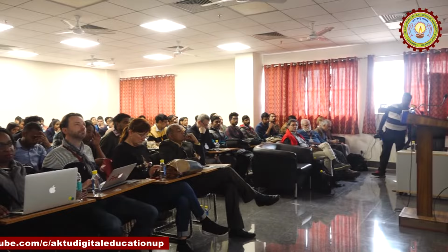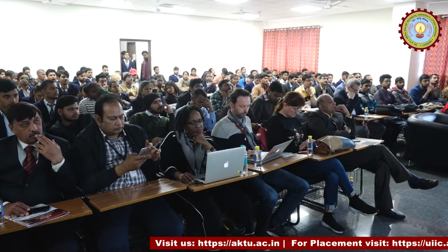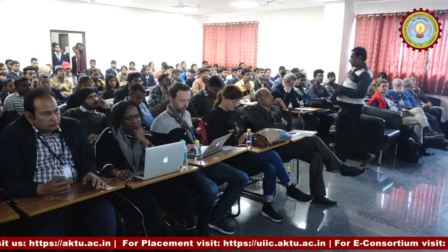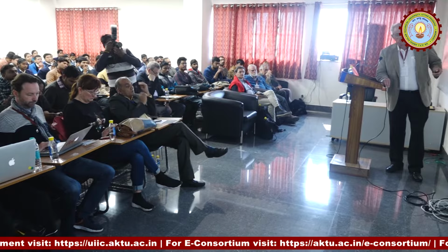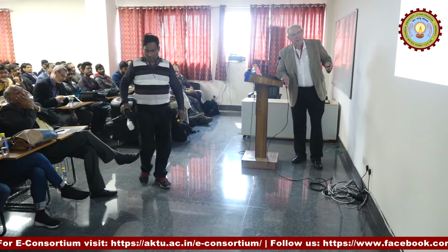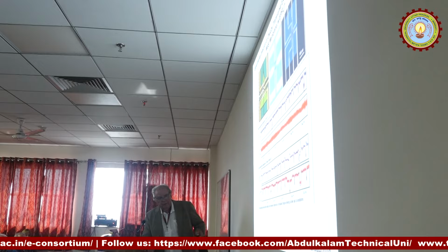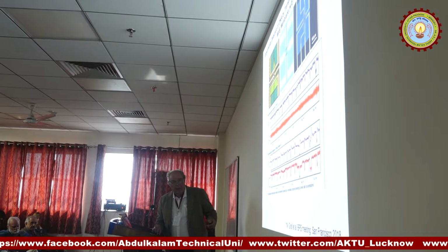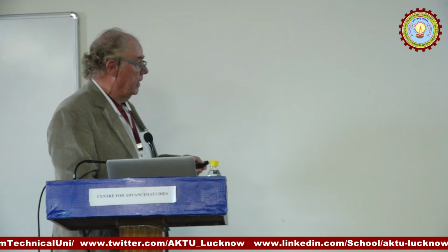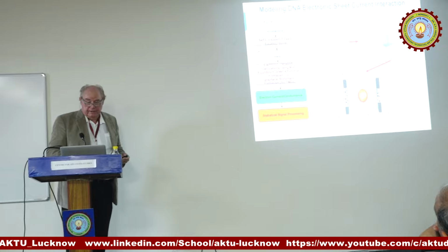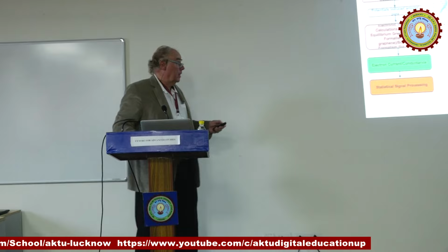Now, we haven't achieved this, but we are now collaborating with the group of Professor Aleksandra Radenovic, which detects electronically now, not only ionically. The dip here detects the DNA. But this is for a certain salt concentration. She had one molar potassium chloride in the material, and as you can see here, we have a lot of noise, but if we can reduce the concentration of the salt, you have a good correlation between the membrane signals. Here is the electrical engineering part. So we had to merge a code, and this is a very intensive kind of simulation process which requires very expensive computer resources.